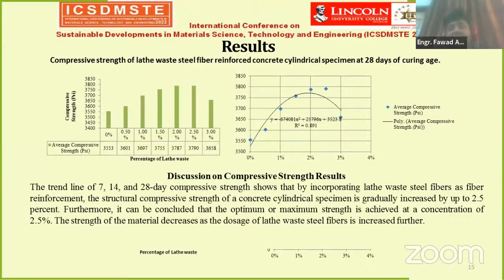Compressive strength shows that on incorporating lathe waste steel fiber as fiber reinforcement, the compressive strength of the concrete cylindrical specimens gradually increased up to 2.5%. The strength was increased only up to 2.5%. By further increase, the strength decreased.